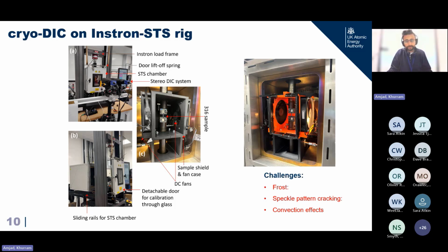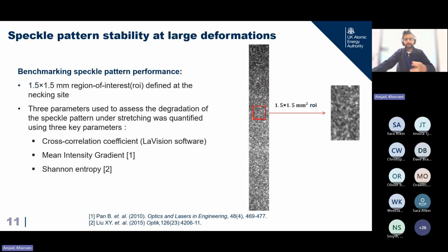We had to minimize frost, which we have done by better sealing the chamber, and then we tried to mitigate convection effects by installing computer fans so that we can create a laminar flow of air across the sample to minimize these variations in the refractive index. So we have done all these kinds of tweaks to the rigs, and we were able to get some initial DIC results. This is just an example of the speckle pattern being deformed at the necking region up to 100% extension.